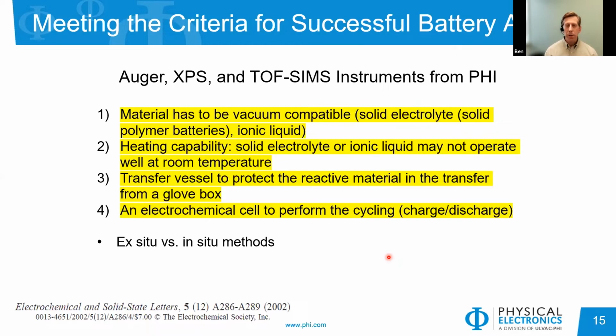Lithium is extremely reactive, and so if we don't handle the samples in very controlled ways, we will get side reactions that we want to avoid. We would also like to have electrochemical cells so we can charge and discharge these batteries in the system as well, again, to simulate actual conditions. Typically, a lot of the cycling is done outside of the analysis chamber, and then the sample is maybe taken apart if it's a coin cell, and then moved in piece by piece into the system. And so you may or may not be getting different results if you had something somewhat in the system already.